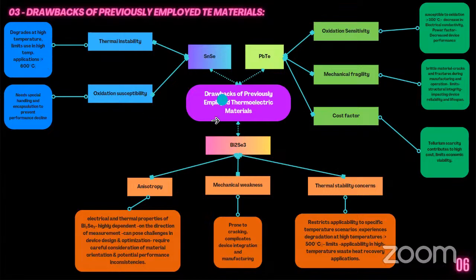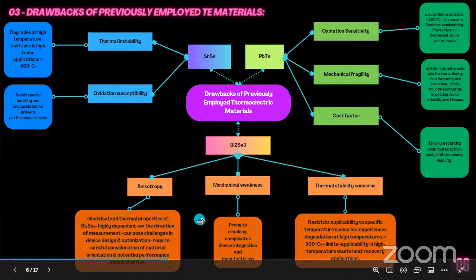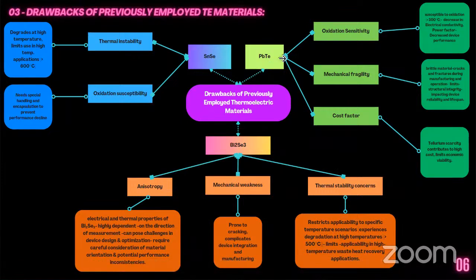While bismuth selenide, even though it is promising, suffers from directional inconsistencies in its properties, making device design difficult. Additionally, it is fragile and degrades at high temperature, limiting its use. While comparing lead telluride, although it is efficient, it is expensive due to the high cost of tellurium. So these drawbacks highlight the ongoing challenges of finding the ideal thermoelectric material, motivating the researchers to develop new materials with superior properties.